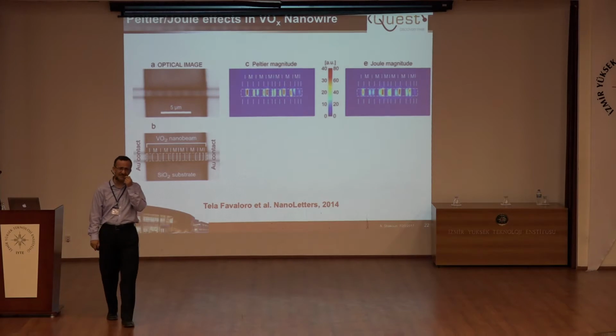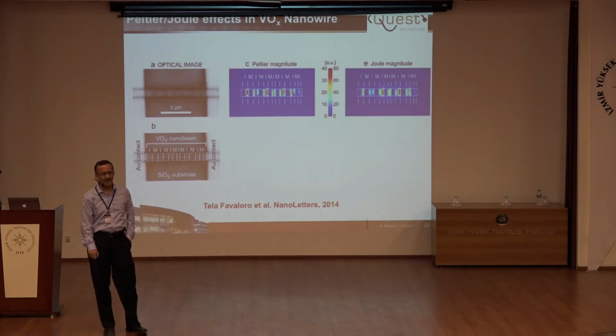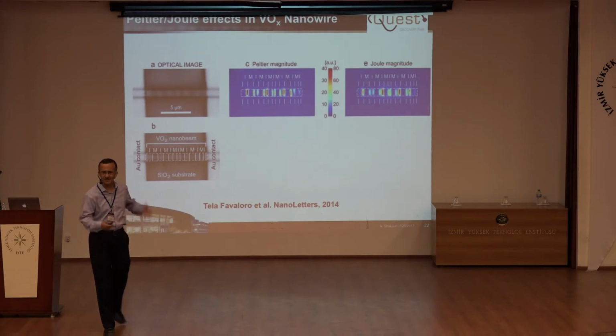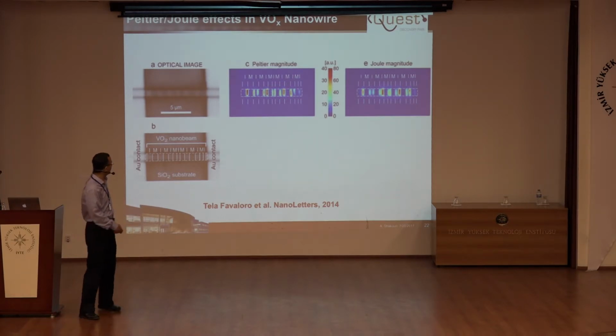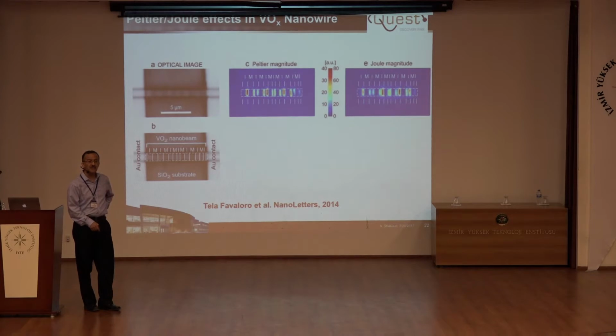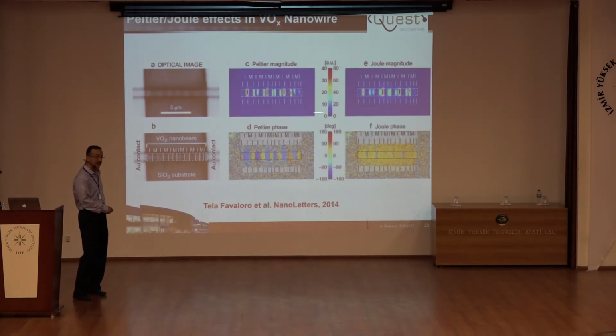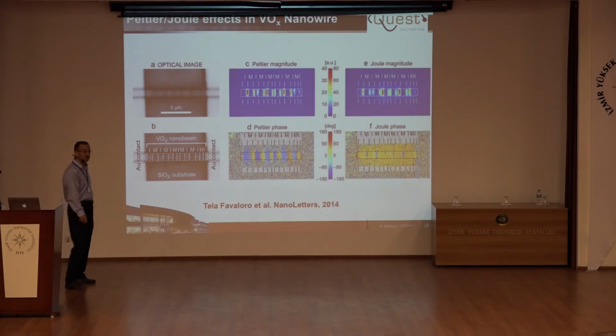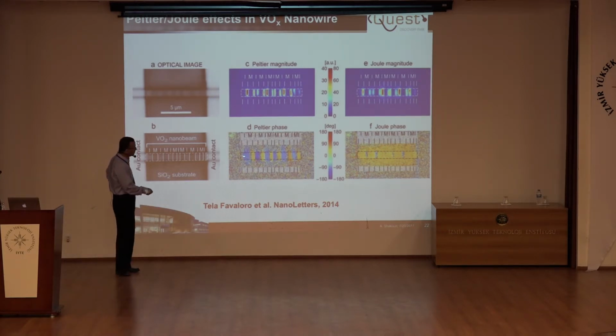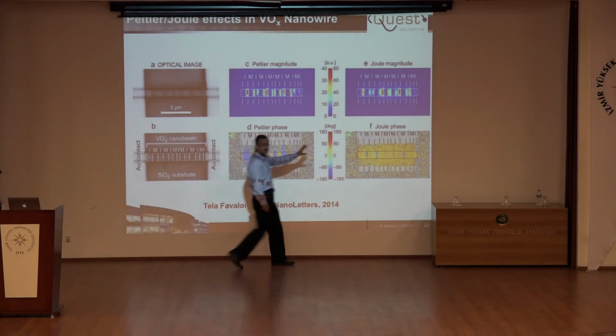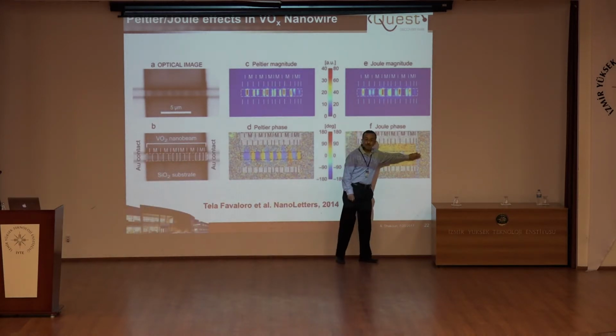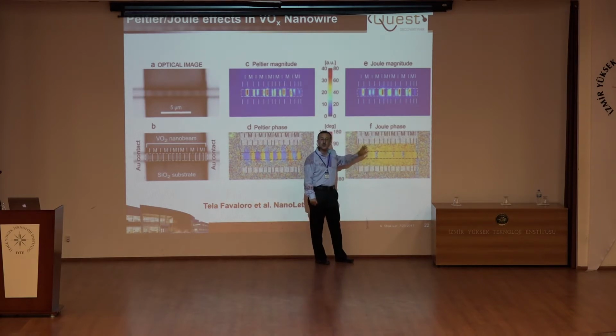As an experimentalist, whenever you have any data, the first thing is to ask what went wrong during the experiment. Is it because there is some mixing, or some way it didn't work? But the advantage of the sinusoidal stimulation is you can look at the phase. The phase tells you much more than the amplitude. And here you see distinct differences. What the phase tells us here is that Joule heating happens in the wire. The heat should go somewhere. The only place it can go is into the substrate.